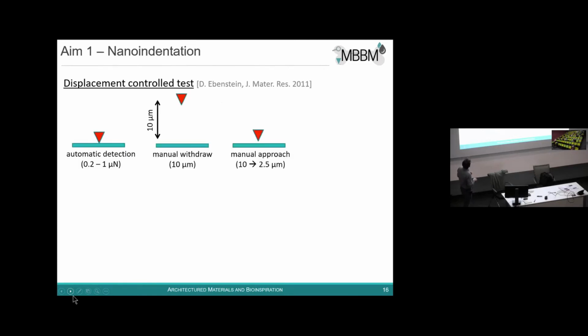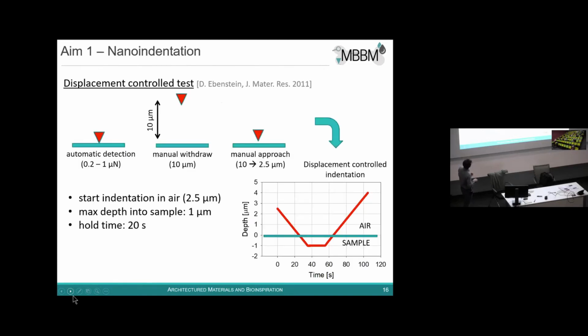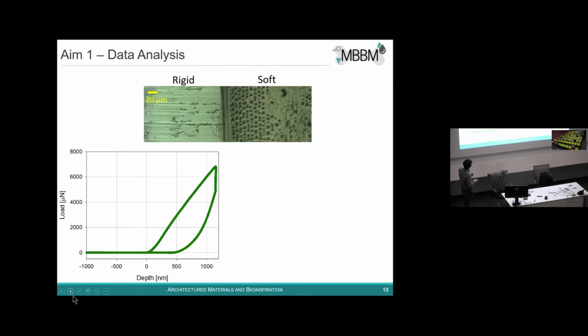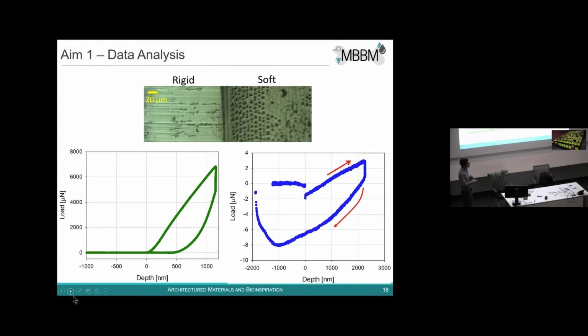So I think here I don't enter too much into the indentation procedure, but maybe I just show you the differences. These are typically load displacement curves when you indent in a hard material. So this is not surprising. This is quite well established. There are established equations to then derive, from the unloading stiffness, from fitting this curve, the reduced Young's modulus, the Young's modulus of the material.